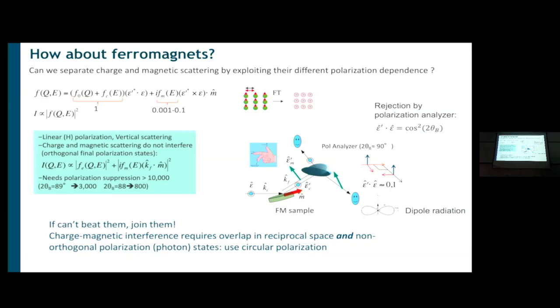But remember what we've been doing, we've been adding these terms in quadrature. And we were saying, look, if you have magnetic and charge scattering, I have one amplitude, completely independent, I add the other one. But this is a complex quantity, and the question is, why don't we have an interference term? When I square this, why don't I have this square plus this square plus the product and the complex conjugate of it? And that's actually what you have. But the trick here is that if you're using linear polarization and the photon in the scattered final state, they have orthogonal polarization states, there is no interference, because to have quantum interference or any interference, you have to have the photons in the same quantum state.